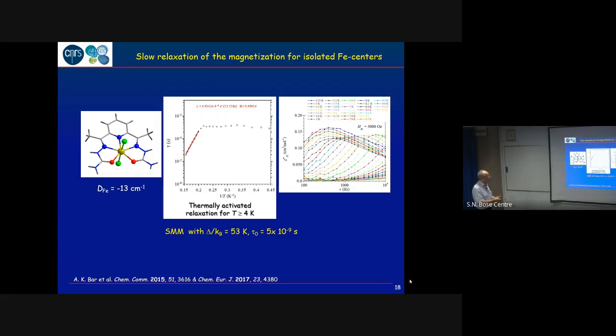And if we plot the relaxation time here versus inverse temperature, what you can see is, first we have a behavior that depends on temperature, and then we have something that depends no more on the temperature. And this is typical for a quantum tunneling effect, whereas this is a temperature-induced relaxation. We can analyze that and extract an energy barrier, and here you have the number we have obtained for this molecule. And this is something we have found for several of these molecules.